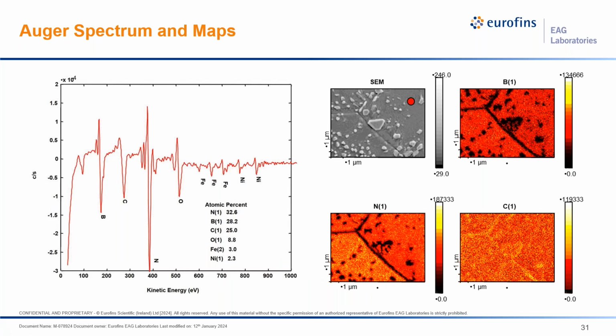So the sample came over to Auger, and we looked at the surface here in the SEM image in an area that the wetting was not working out well. And the survey spectrum from this location was dominated by boron, nitrogen, carbon, and oxygen peaks, with some of the Kovar peaks present, but at low levels. Since Auger is a scanning electron probe technique, we can also generate some maps, as we see here on the right, and we can see a uniform coverage of the boron, nitrogen, and carbon contaminants, which were not detected at all in the EDS. We also note that the Kovar peaks are present, and since the sampling depth is about 5 nanometers, we know that this is indeed a thin film contamination layer because we can see through it and pick up a little bit of the Kovar peaks.